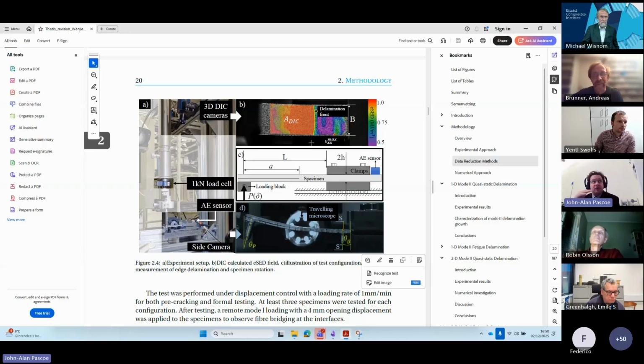Also, another size effect is if you have a multi-directional layup. We've done some tests of multi-directional layups. Then you get this kind of migration effect, and then you get a fiber bridging-like behavior. Again, we can argue about terminology, right? But you get bundles of fibers that get pulled out but are still attached on either side.